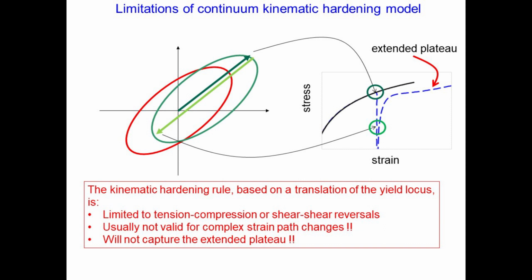So this is the stress acting at this point. So when you reverse the shear, then you go through zero, and the reversal finds the yield surface much closer to the origin. So you have a lowering of the yield stress. So you are here. This point is there, and this point corresponds to the yield at this position. So they say, okay, with this we solve our problem of the reversal effect, the stress differential.